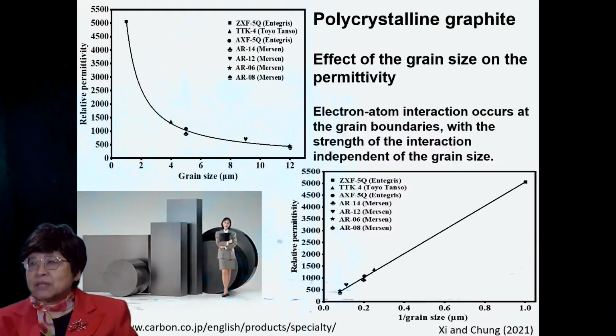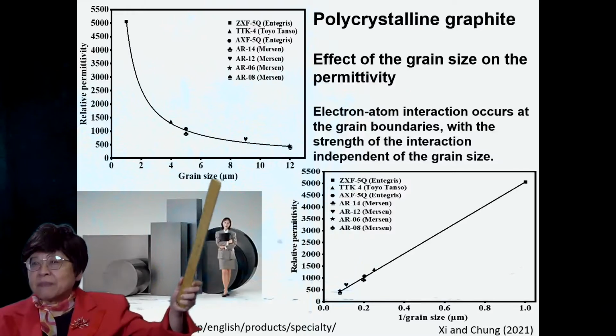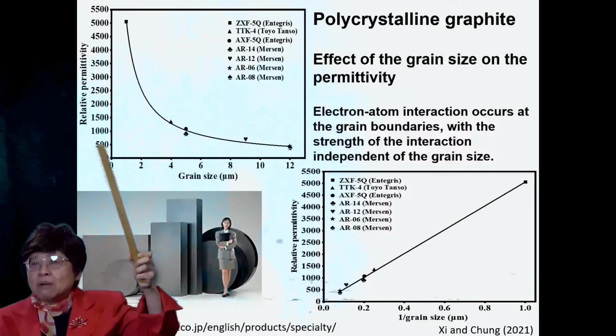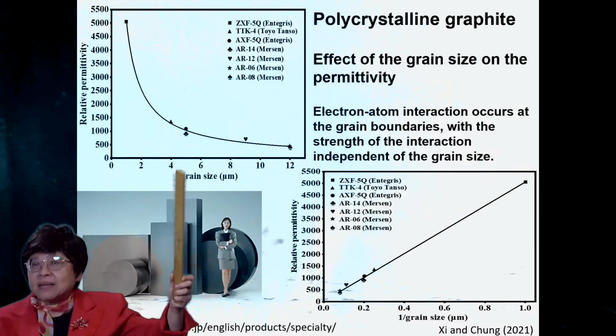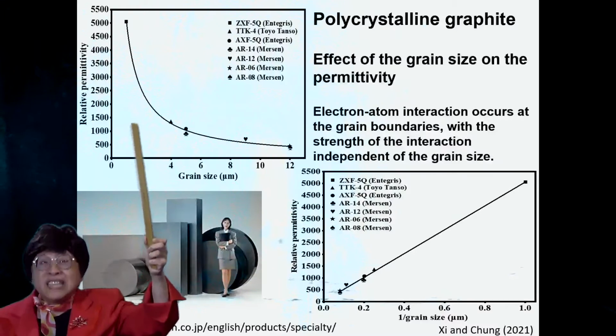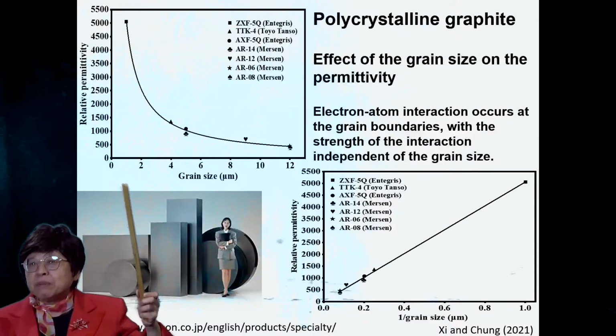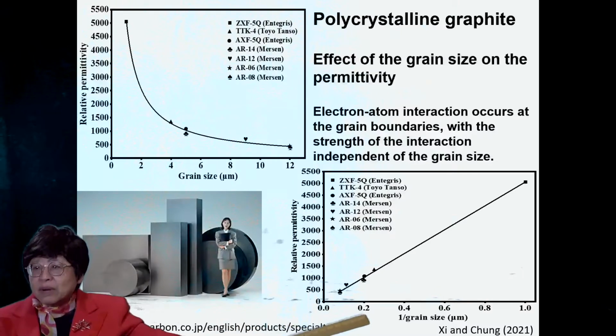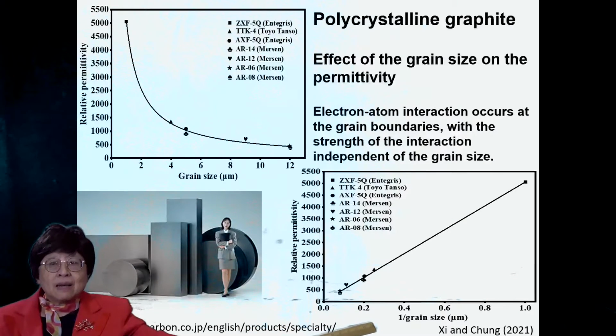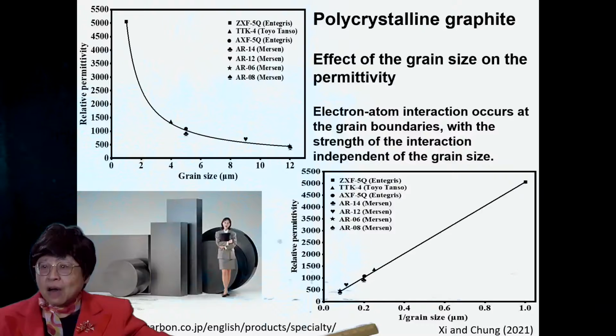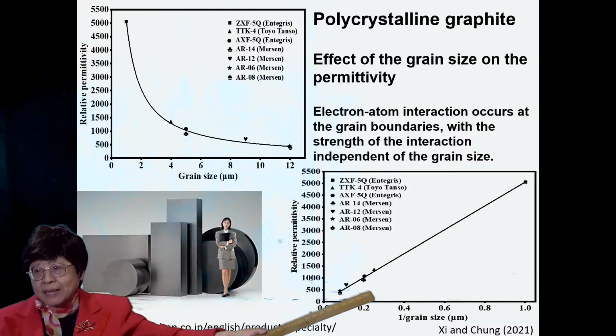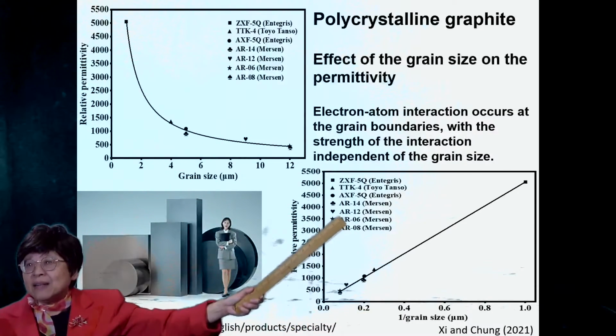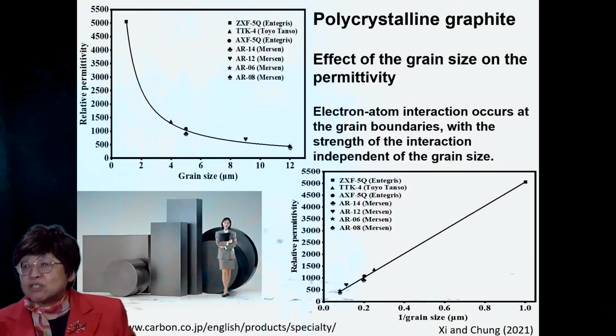And this is a polycrystalline graphite and showing the relative permittivity decreasing a lot with increasing grain size, increasing a lot with decreasing grain size. If one plots versus 1 over grain size, which relates to the grain boundary area per unit volume, one gets more or less a straight line. And that indicates that the electron-atom interaction occurs at the grain boundaries.